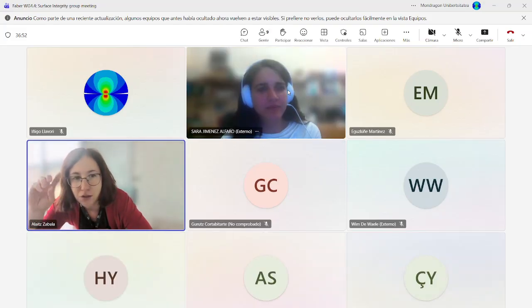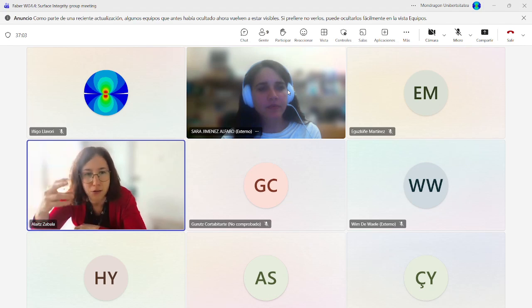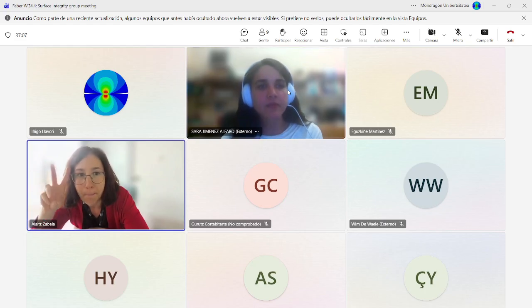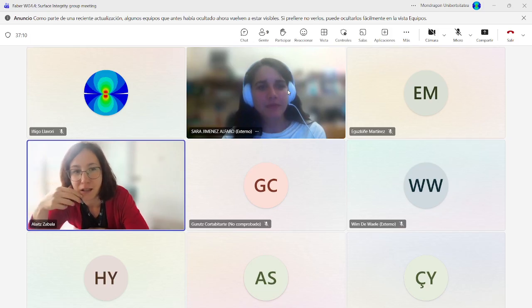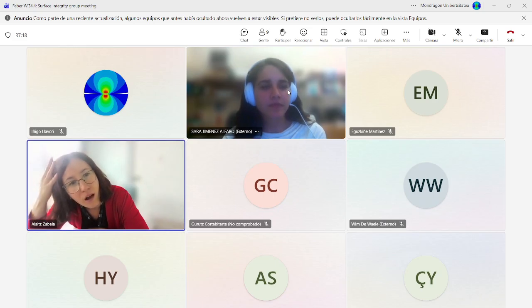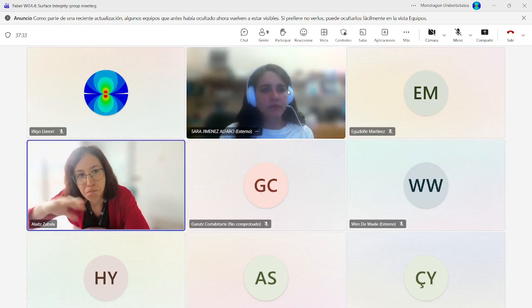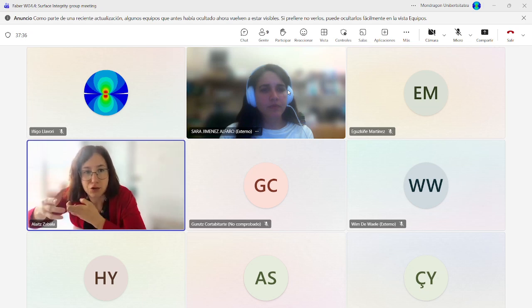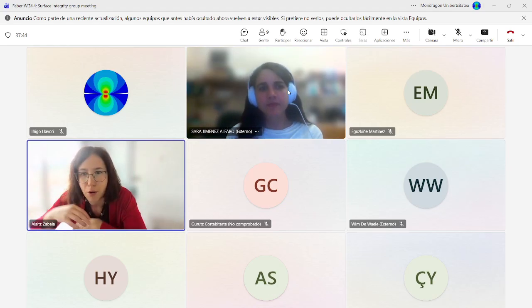At the end, you mentioned both additive manufacturing and pitting corrosion. In the case of pitting corrosion, I still think it's very good because normally one profile could describe in a proper way the profile of the surface, from the point of view of fatigue. I was trying to think about additive manufacturing because the topographies of additive manufacturing are not such repetitive patterns anymore. I was also thinking about grit blasted surfaces that probably are not fully described by a profile. I don't know if you have any approach for including the 3 dimensions or non-repetitive patterns, something more like a 3D approach.